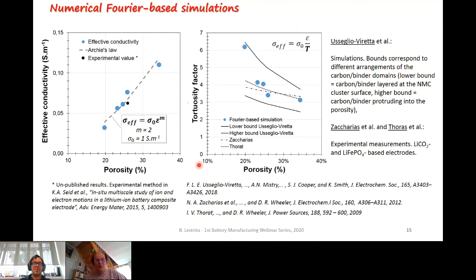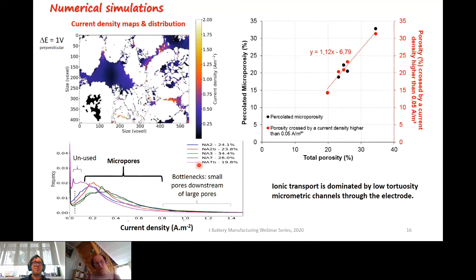Because we are confident in these simulations, we are now looking more locally at what's going on. And here you have a current density map. The potential difference that was applied to realize this simulation is perpendicular to these 2D slices, and the color is showing you where the current is mild or medium in blue, to where the current is high in red or bright yellow. And you have here the current density distribution. When you look at these pictures and the values, you realize that the major part of the current is crossing the micropores, the micrometric channels.